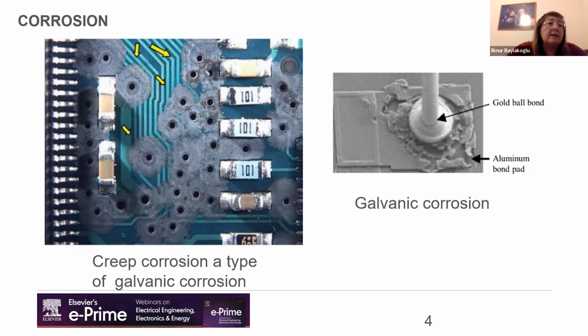As you can see here, there is a creep corrosion, and this one is an example of galvanic corrosion. Actually, galvanic corrosion could be because of the coupling between, for example, aluminum and gold with the presence of a water film on the surface. The water film works as an electrolyte, and the electrochemically active aluminum becomes the anode, and it corrodes. At the end, metal oxides are deposited on the gold.